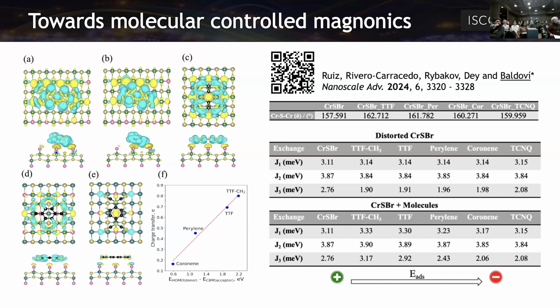Yeah, but the effect, for example, when you have the magnetic effect, no, you can have a molecule that also is spin polarized. Then you have a magnetic dipole there induced, and with light, you can control the molecule to create the spin wave. No, this is like amplifying, for example, the signal of the light towards a molecule, depending on the energy levels that this molecule has. So it makes a lot of playing for the chemists, no? Like to think about which are the best combinations between one material. With light, it's possible to generate, and you can tune, but you have much more versatility because you can combine both effects. You can combine light with the molecule and then the material. It's more complex at the end, but it's a richer playground, as you say.